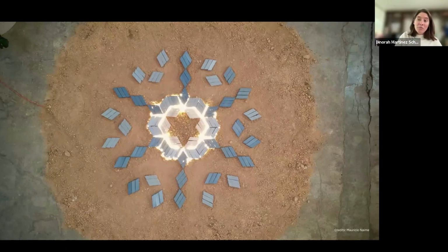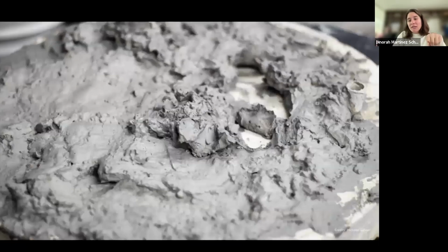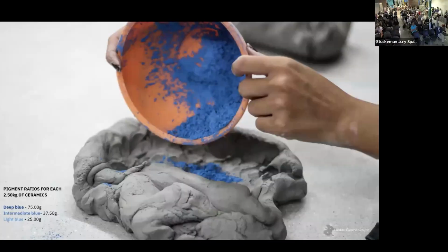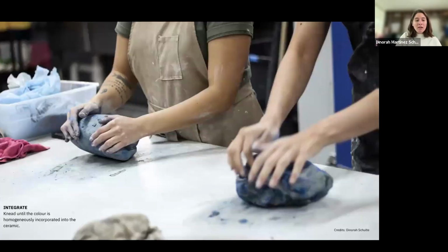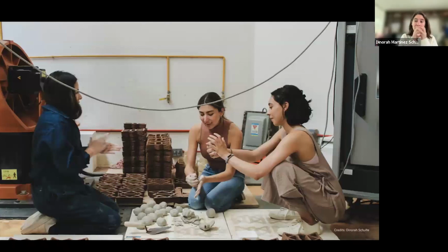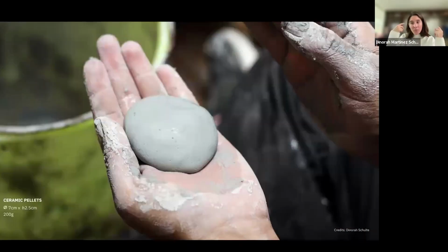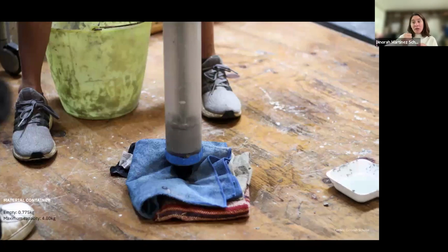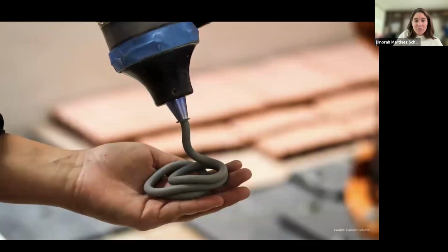And one of the most interesting parts is the pigment. So how do we create this kind of pigment? This is the normal natural color of the clay. Then we started to add the pigment in different gradients: the blue, intermediate, or light blue. And then they kneaded it for 20 minutes, totally by hand. And then they prepared these kinds of bullets to create a more optimized and faster production, to fill the tube for very fast 3D printing production. And then we get the blue pigment inside the normal ceramics through the material process.